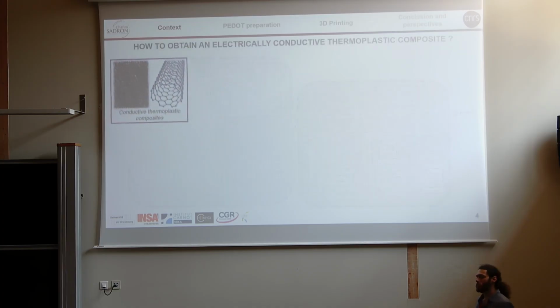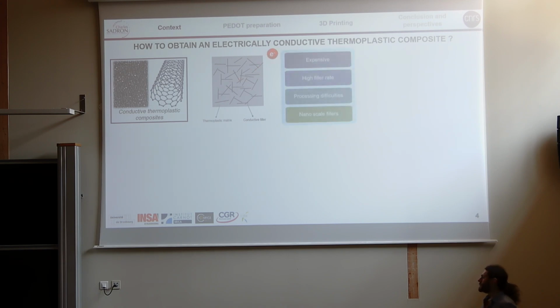So how do we make such materials? The most widespread strategy relies on the inclusion of conductive fillers into an insulating thermoplastic matrix. And once you reach the percolation threshold, you allow the current to go through the material. There are still a few drawbacks because this method is expensive and is linked to the use of a high filler rate, leading mostly to processing difficulties.